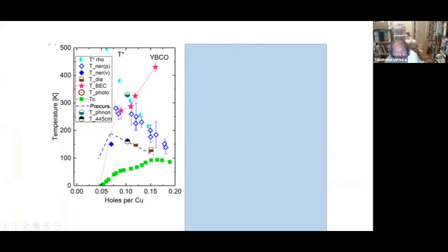Now let us see the case of YBCO. This is kind of controversial, and so I left it up to here. Firstly, the Nernst effect and diamagnetic susceptibility were reported, and they are showing a very similar situation as in the case of LSCO. The Nernst effect reported by Taillefer's group includes the quasiparticle response, and it is therefore following more or less this T-star line.